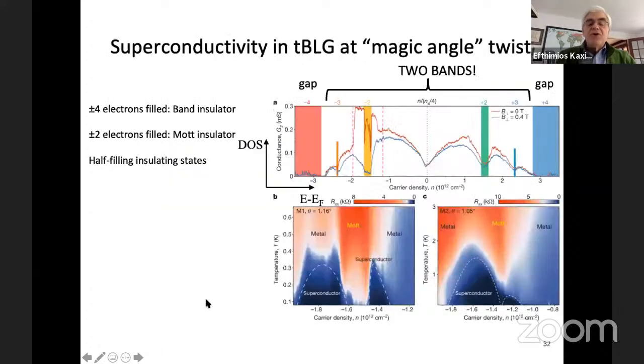So that's why having a detailed atomistic-based theory can provide this powerful tool for making useful predictions. So what about the superconductivity that I was mentioning? So here's again the plot that I showed you earlier. This is the density of states. These are large gaps at the two endpoints, and these are smaller gaps at the middle. So one hump like this corresponds to a complete band. This is another band, and these are small gaps within the bands.